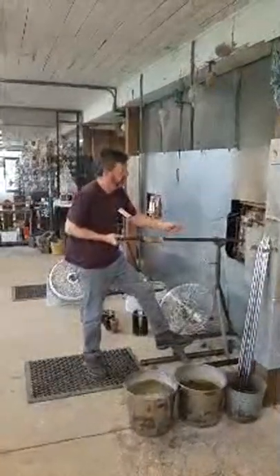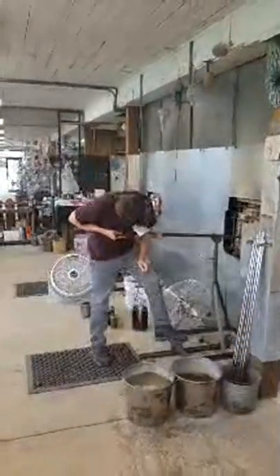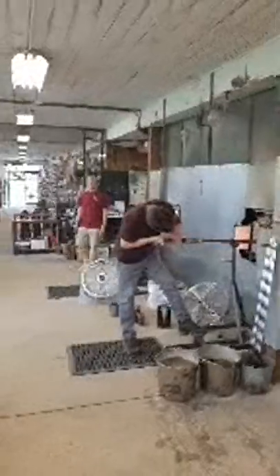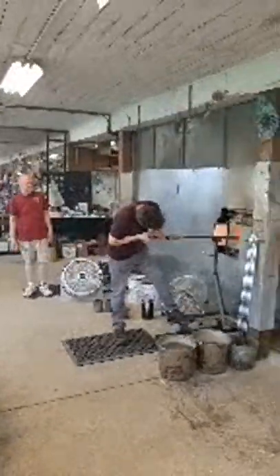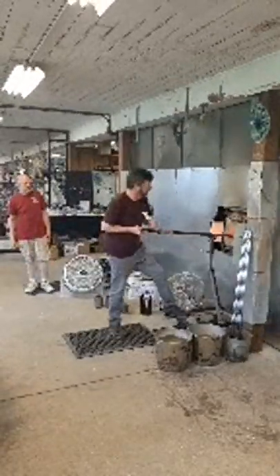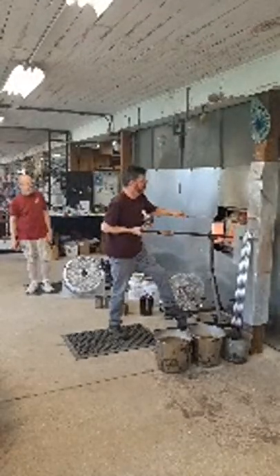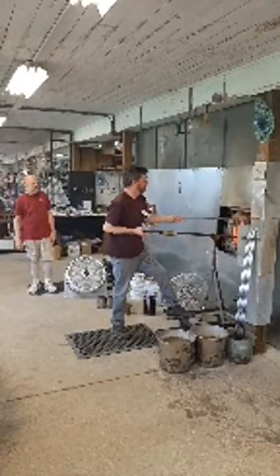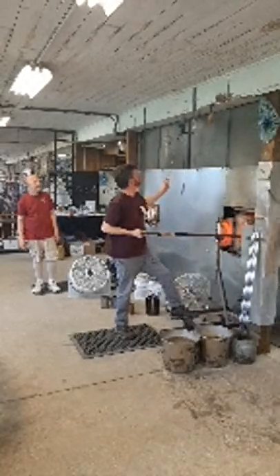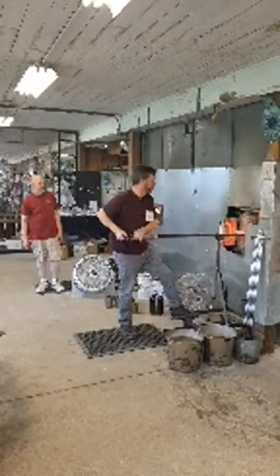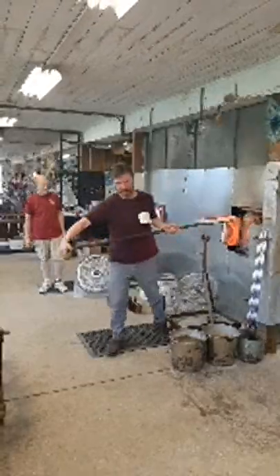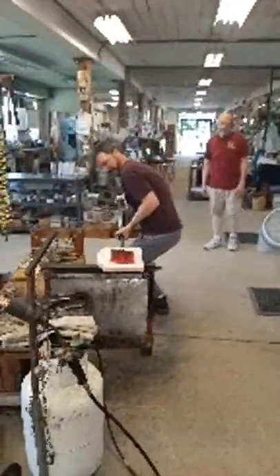Once he's satisfied that he's got the thing fused together, he'll be ready to pick it up. He doesn't really want it to melt, so if he gets to a higher temperature like 17 or 1800 degrees, it'll only be for a few moments. He'll probably do his pickup at around 14 to 1500 degrees, I'm guessing. But we don't really have a thermometer to put on it, so it's more feel by how the glass moves and appearance. He can take that tagliole, that blade he showed you earlier, or a pair of tweezers.